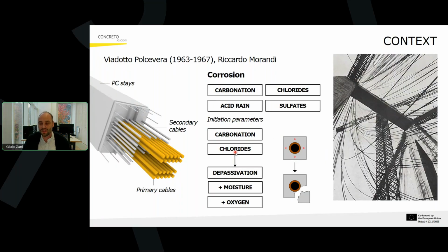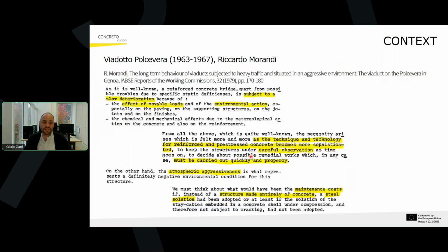So in general, if you have a structure, for instance this bridge, which is subjected to carbonation and the presence of chlorides, which might be related to airborne salinity or also de-icing salts, this leads to the depassivation of the reinforcement. But in order to develop some corrosion products, you always need also moisture and oxygen. And this finally leads to the creation of corrosion products, which have a volume which can increase about 7 times with respect to the original material, inducing some self-stresses and finally the loss of the concrete cover. Moisture is one of the ingredients that, in my experience, I always observed in all the structures which were severely corroded. So it's a very important ingredient.